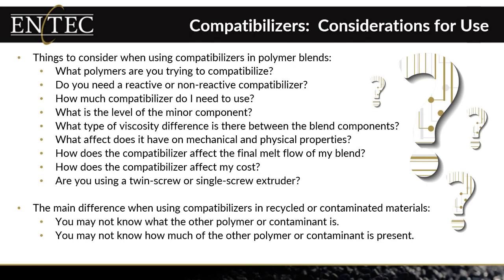So some of the considerations when you're thinking about using compatibilizers. If you're making a polymer blend, obviously you need to understand what are you trying to compatibilize? What are those two polymers that you're talking about in your blend? You might need to think about whether you want a reactive or non-reactive compatibilizer. Why is this important? Aside from the performance aspect, there may be a cost aspect to that. And one thing I didn't mention on the reactive compatibilizers is they do tend to have a very negative effect on the melt flow of your final compound. And so if high melt flow of the final compound is required and your application will allow you to use a non-reactive one, that might be something for consideration.